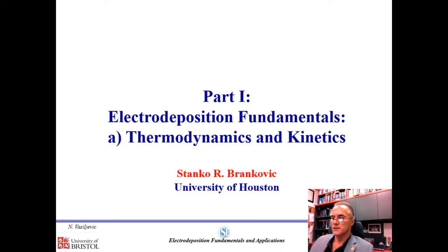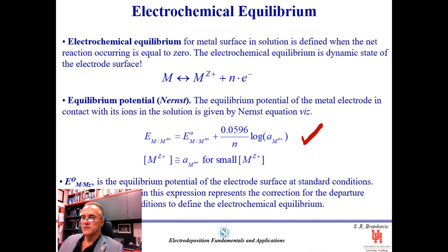We will start first with the electrodeposition fundamentals and we will discuss certain terminology. First, we have to understand that electrochemical equilibrium is a dynamic equilibrium, which basically means that at the electrode surface we have electrodissolution and electrodeposition of the metal going on at the same time. In equilibrium, both reactions occur at the same rate and therefore the net reaction is zero. The equilibrium is defined by the potential at which the electrode is resting, which is defined by Nernst. The Nernst equation shown here presents the value of the potential that we need to hold the electrode at in order to secure the equilibrium.